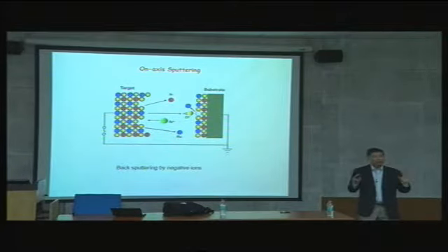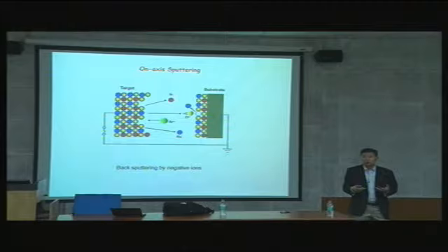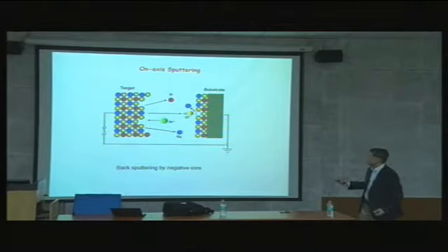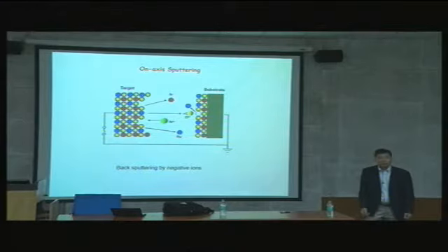You're actually putting 100 times more argon gas in the chamber, which means 400 or 600 millitorr, 100 times more. Your mean free path is very, very short. Then the oxygen ion scatters so many times, and when it reaches here you lose most of the energy, so you don't have such strong backsputtering. But the problem is there's so much scattering that you also don't get the flux.